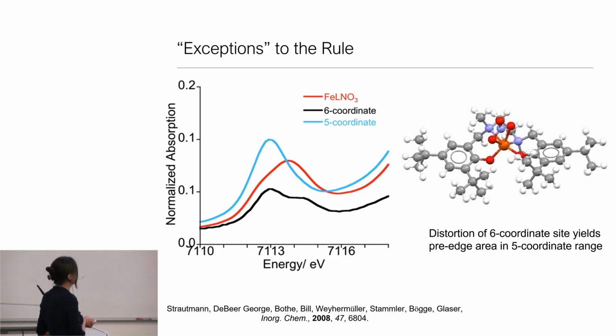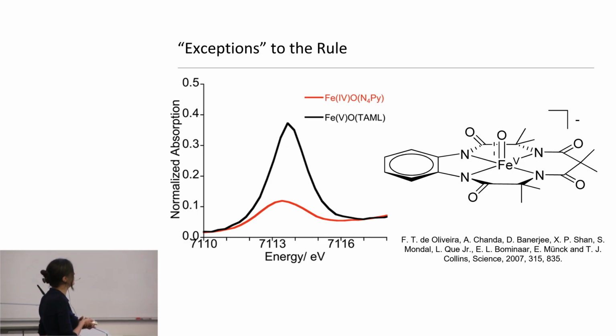Let's look at the other exception to the rule, and that is this idea that these pre-edges have to shift by 1 eV per unit change in oxidation state. These are complexes that by Mössbauer we assigned as iron 4 and 5 complexes, but you actually see that from the pre-edge they're nearly identical energies. The reason the iron 5 in this case, the black one here, is not at higher energy is because it's actually 5-coordinate. And so the ligand field locally decreases and the 3d manifold drops down. What you do, though, beautifully see is that because it's 5-coordinate, it has a mechanism to gain intensity in its local C4v geometry.